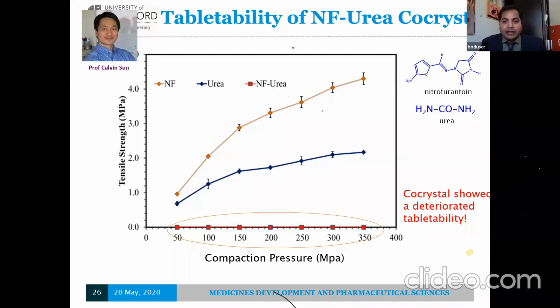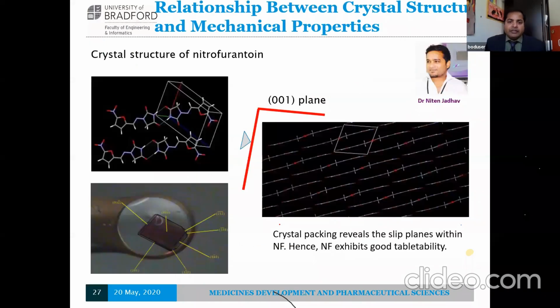Nitrofurantoin has a higher tensile strength compared to urea, and the co-crystal in fact has shown poor compressibility properties. So then we try to look at the crystal structures and see if we can understand anything.